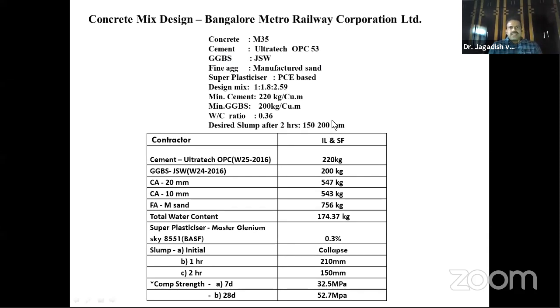Okay. This is the mix design used in Bangalore Metro Railway, as I mentioned earlier, wherein they've used PCE-based superplasticizer. Here they've used 220 cement, 200 kgs GGBS, and water cement ratio is almost 0.36. And then slump, you can see it's a collapsed slump, and after 1 hour and after 2 hours, because it has to be placed. It's a flowing concrete. 28-day strength, it is an M35 grade of concrete. They've got 52 MPa. This is one of the mixes you can see.